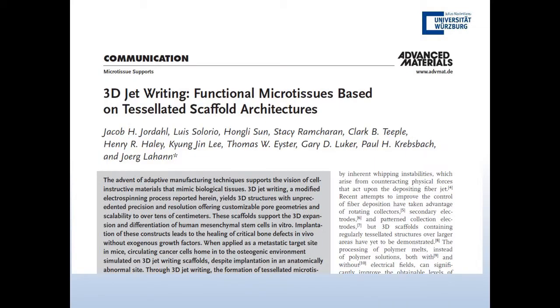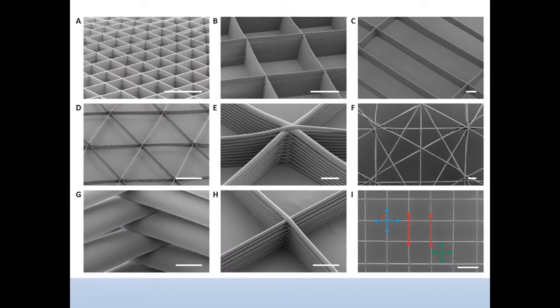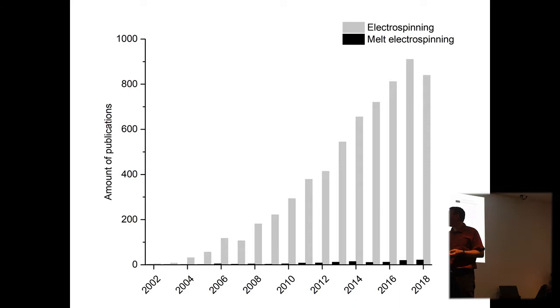In fact, this is a recent paper where they call it 3D jet writing, where PLGA is dissolved in a very high concentration, I think within chloroform. And so you can actually do writing, and these are actual SEM images. So nice structures. The difference with melt electrospinning versus this 3D jet writing is that this box size is really large. Yeah, so this I think is about 1 millimeter in size. I think as they start going closer, they have more instabilities. But it's an interesting demonstration.